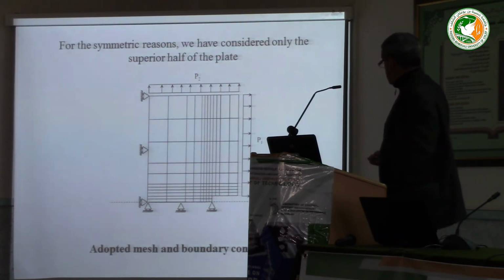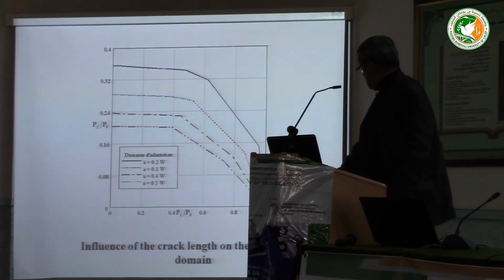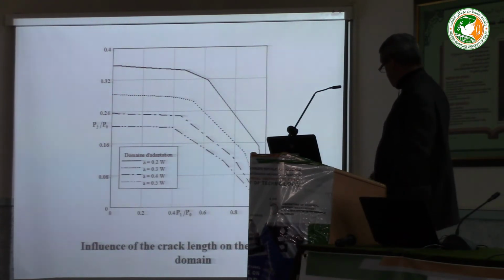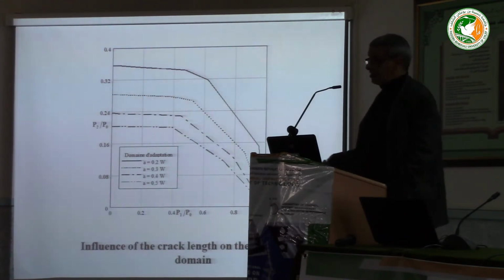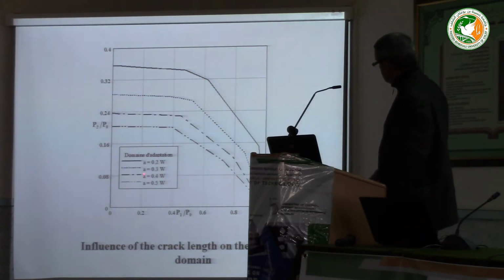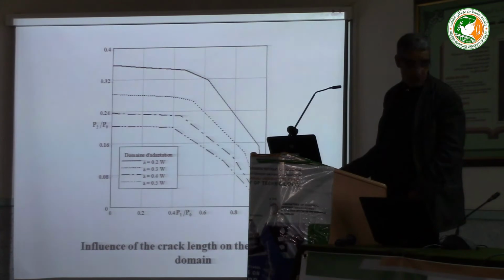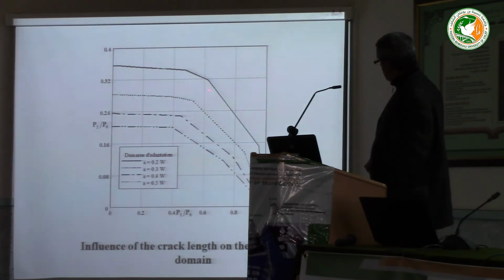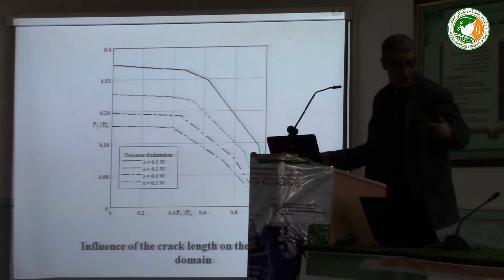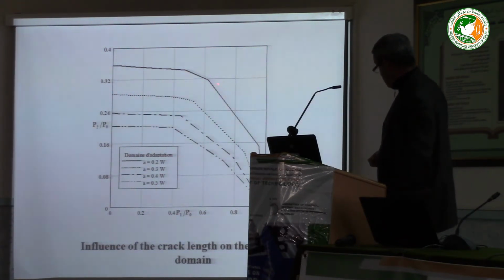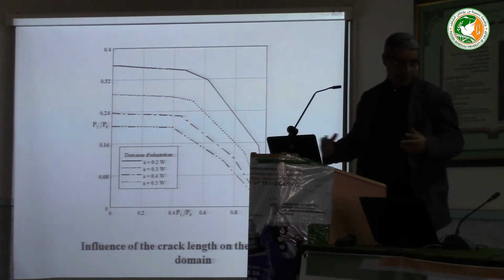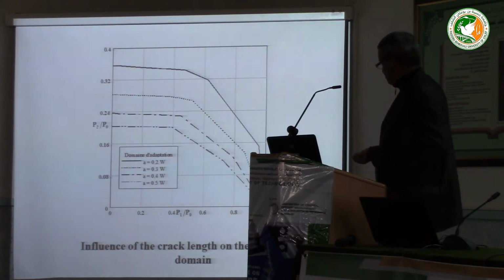For symmetry reasons, we have considered only the superior half of the plate, and we show here the adopted mesh and the boundary conditions. We have plotted the shakedown domain, which is a safe domain, according to the crack length, 0.2 the width of the plate, and we see that this domain is reduced with the augmentation of the crack length.